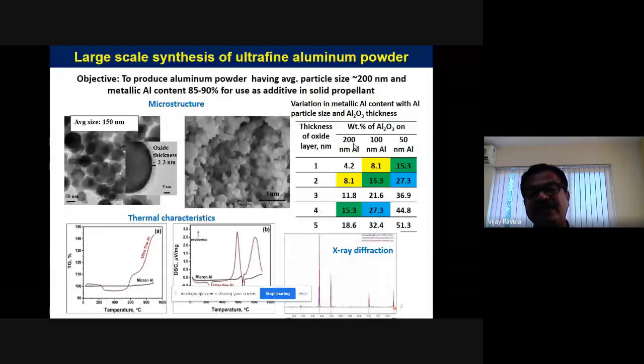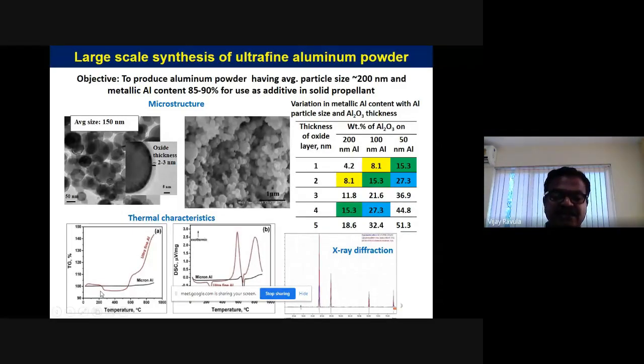And typically what we made is an aluminum powder. So we have nano aluminum powder. Aluminum as such is used as an additive to solid propellant. When you reduce the size, the oxidation kinetics are faster, because the diffusion length of the oxygen is smaller, and that's the reason you go to nano size: the energy release will be higher. If you see the thermal characteristics, the finer the size, the higher the oxidation rate, as well as the higher the heat release.